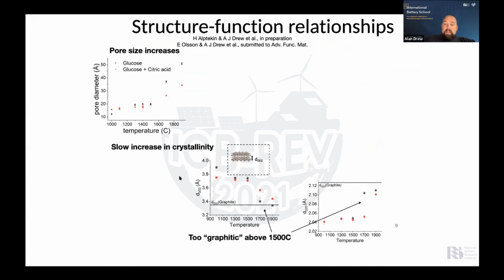Okay. And at the same time, the distance between the graphene sheets in the material moves from a high value to a value that is found in graphite. Okay, and it's the same here with D020. This is D002. This is D020. And you can see it moves up towards the graphite value as you increase the temperature. So what's happening is we have a pore size increase and a slow increase in crystallinity as we increase the